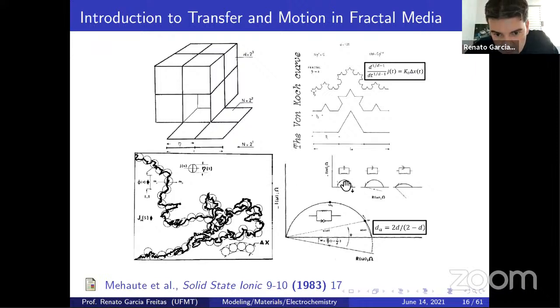So if you take a look here, we have a semicircle with a capacitance in parallel to a resistance, and a perfect semicircle impedance. As soon as we increase the fractal dimension, like here, from this one to this one to this value, we see that the CPE, as we used to say, goes lower, isn't it? We have a parallel, it's a nomenclature. So we have a small CPE, a high CPE, and a higher CPE, and the CPE here is increasing only with the alpha value, the fractal dimension.